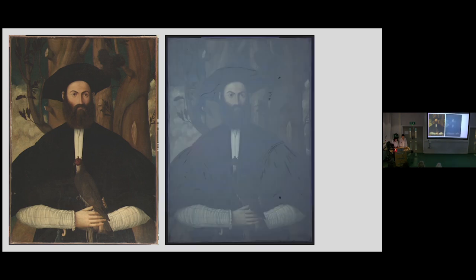From observation under UV fluorescence, the varnish layer is pronounced and the more recent retouchings are made visible. Its latest intervention was its examination and preparation for a loan in 2017, when the gallery's chief conservator retouched specific areas using gamblin colors and MS2A varnish. The aged varnish had discolored and yellowed, and it is currently distorting the intended chromatic relationship of the composition.